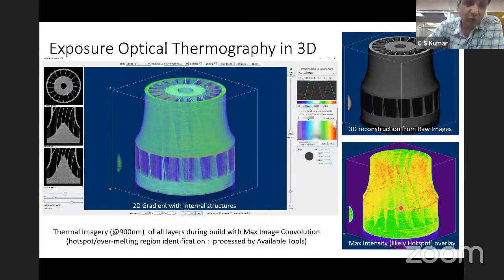So we reconstructed the same job that we see. Since we did this, we could actually build this up. This is not on the same scale as what you saw there, but I can see here the supports as well as the internal ones, and I can examine this at any cross section and then come up with alternative recipes to achieve this. This is an example which shows where the likely hotspots are and the chances of having defects inside the part. As I said, if I put this to use in real life applications, you don't want this part to fail. It has to withstand a long life of maybe 40, 50 years in turbines, and the failure expectations are very low there. So it's pretty challenging to do it by this method.